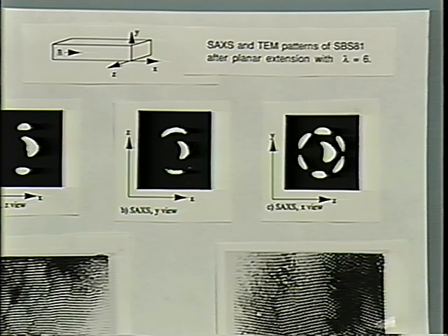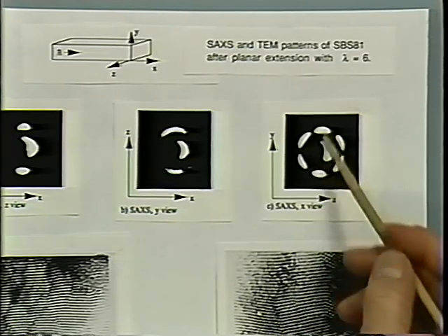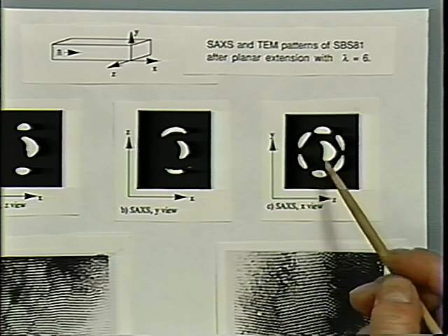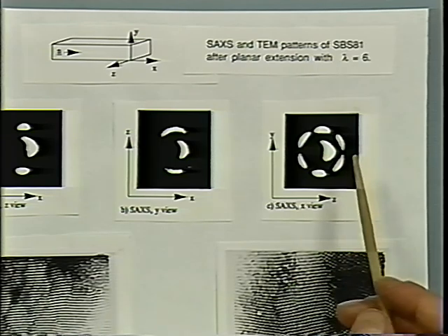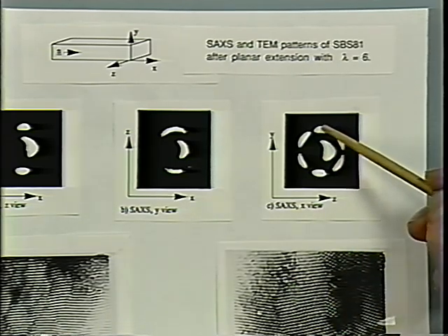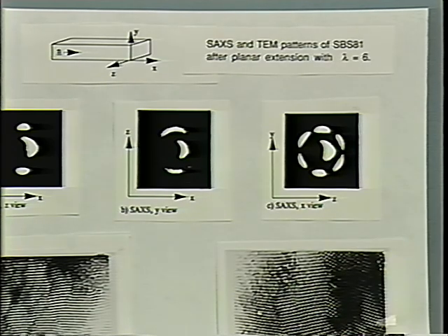Two observations. The alignment is parallel to the sample, or to the squeezing direction. It's parallel to the sample surface, and you can see this because of the reflection on the top and on the bottom. And from our initial picture, if I can find that, you can see that this was reflecting a special type of order.